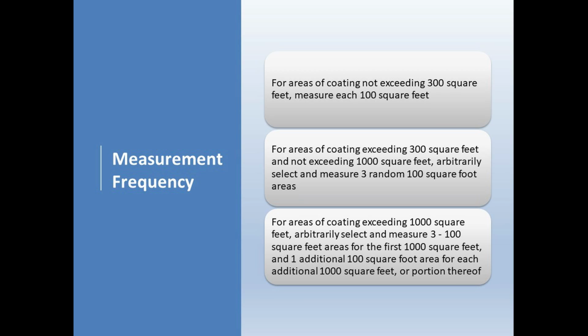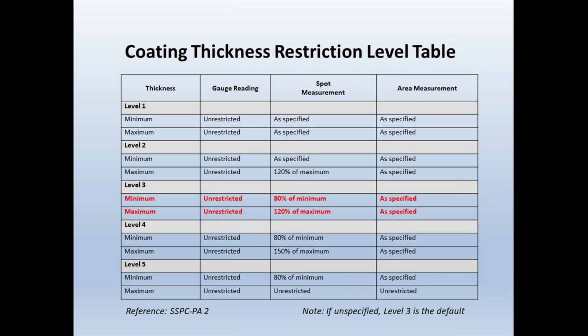Okay. And there's the criteria: less than 300, 300 to 1,000 square feet, and then over 1,000 square feet of coated surface. How many areas you check. In each area, you're always taking 5 spot measurements, and you're always taking at least 3 gauge readings. And then SSPC PA2 has actually established some thresholds on how far out of spec the spot measurements are allowed to be and still be acceptable.